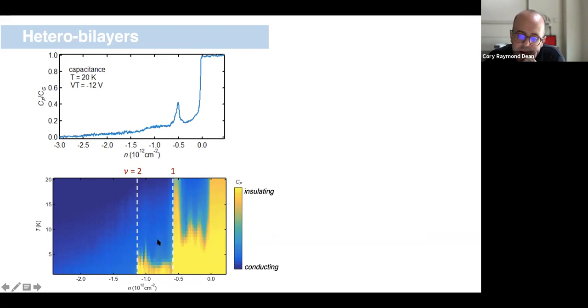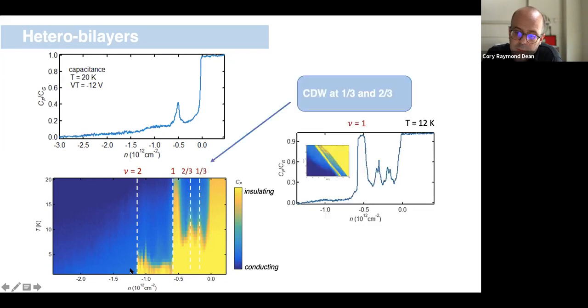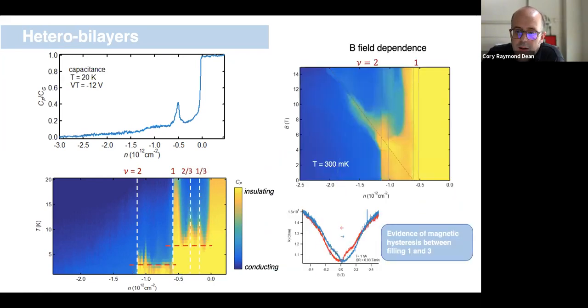So our interpretation of this data is that, in fact, the whole system basically is localized. And it might be the case that it's localized because the Moiré potential is so strong in the system. So we imagine that our electrons are just localizing on the Moiré sites for all fillings in the flat band. And then as soon as we exit the flat band, that's no longer the case. We now have a compressible system again. Okay, I'm going to skim some of these details.